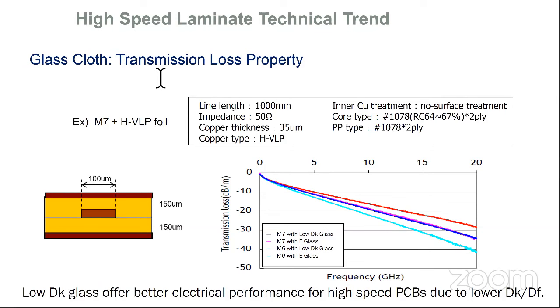Continue on the topic of glass cloth and its contribution to transmission loss. In this particular example, our test vehicle uses a 1,000 millimeter length circuit, 50 ohm target, 1 ounce copper using HVLP copper. The resin content on the dielectric for this particular TV is 1078 glass with a resin content between 64 and 67%. And that is the core. And then the bonding ply is also a 1078 glass 2-ply. So we need to keep those things constant as we do these types of measurements.